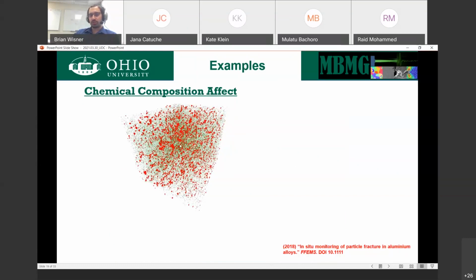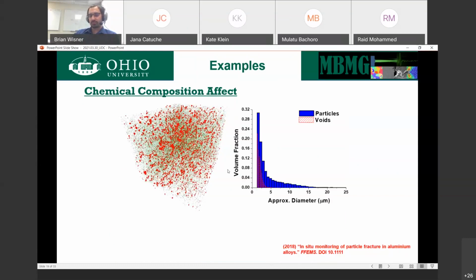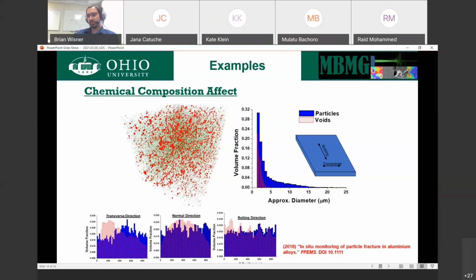The red are the particles, the green small dots that are very hard to see are voids. So this particular material was hot rolled, and we achieved a material that has very low voids, a very small amount, and not too many particles. And we characterized how they're distributed in space. So in this process, we achieved a material that has particles fairly uniformly distributed. The particles in this case are represented by the blue histograms. And we have voids that are not quite uniformly distributed. They seem to be predominantly existing below the surface in the normal direction. So as we rolled, we essentially affected how the voids on the surface are in comparison to the ones below the surface. That's going to change the way it behaves.